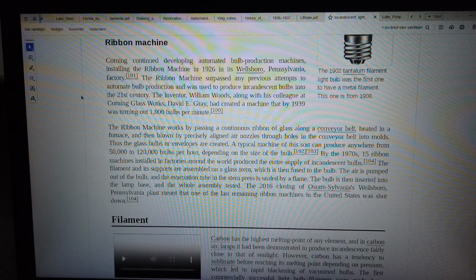The ribbon machine works by passing a continuous ribbon of glass along a conveyor belt, heated in a furnace, and then blown by precisely aligned air nozzles through holes in the conveyor belt into molds. Thus the glass bulbs or envelopes are created. A typical machine of this sort can produce anywhere from 50,000 to 120,000 bulbs per hour, depending on the size of the bulb.